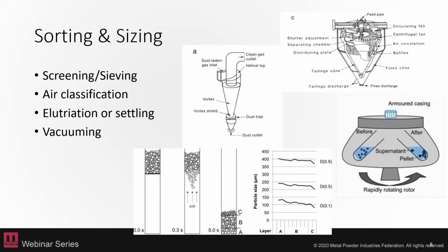And the air classification is typically more expensive than your standard screening sieving. That's your cheapest method for classifying your powders. And then the air would be used more on the under 20 micron size powders.